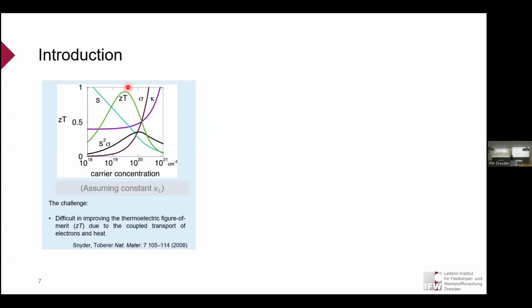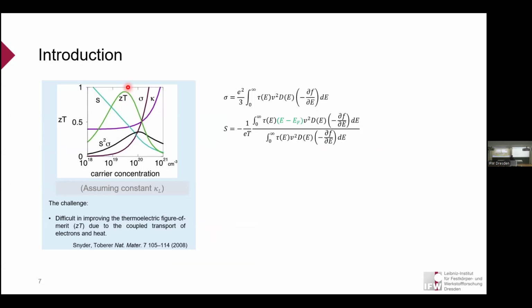If we look deeper into these curves, using the Boltzmann formalism, the conductivity increases with higher carrier concentration because we have a higher density of states. Meanwhile, for the Seebeck coefficient, there is a decisive factor, E minus EF. Basically, when you change the energy of the carrier across the Fermi level, you get a sign change of the Seebeck coefficient. That means different charge carriers will counteract each other, so you will not get a very high Seebeck coefficient.